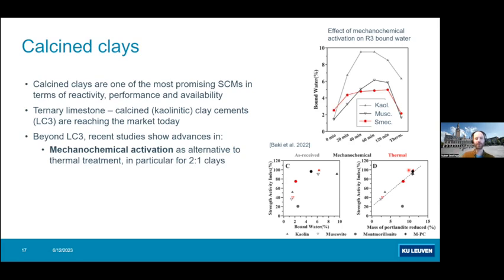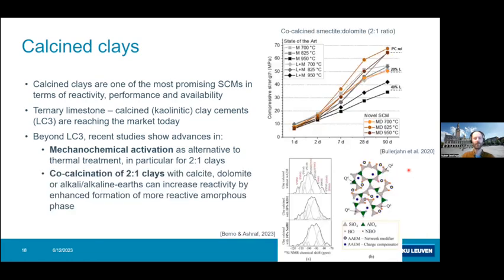What we see beyond these LC3 cements is that recent studies show that you could also try to use mechanochemical activation, so intense milling, as an alternative to thermal treatment, in particular for those clays that are a bit less reactive, so the smectitic or the illitic clays, not the kaolinitic clays. And co-calcination of these so-called illitic or smectitic clays with fluxes or materials containing fluxes such as calcium or sodium or potassium can increase the reactivity by enhanced formation of reactive amorphous phases.